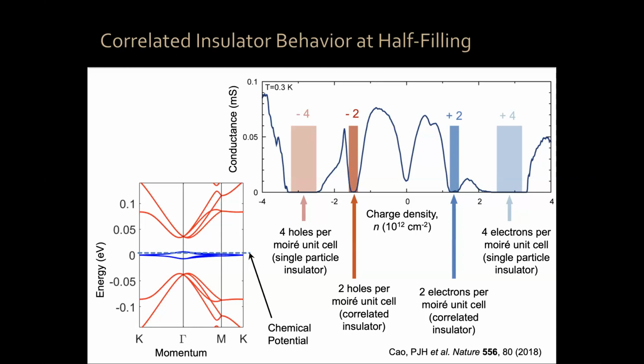I didn't put the twist angle here, but this one is actually 1.18. For angles larger than 1.1, particularly 1.15, 1.17, 1.18, the TCs are smaller, and the situation in terms of the insulated states becomes a bit more symmetric. And often we don't see N equals 3. For example, here we didn't see the insulated state at 3. You see this wiggle? This wiggle is occurring at 1. But it's extremely twist angle dependent, in a way that is not understood yet and mapped in detail.